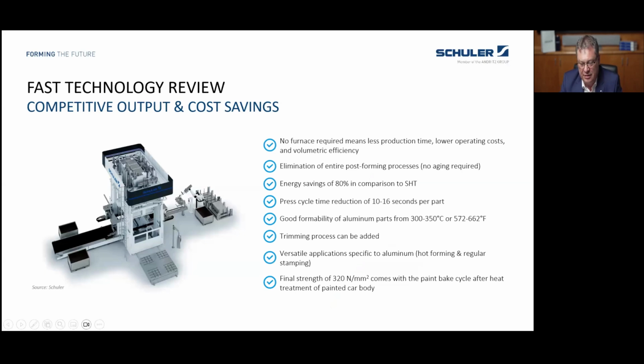Yeah, so to sum up all the aspects, the big benefit of the process is that we don't need any furnace for heating up the blanks, and this will of course lower the operating costs and also the required space for the line. We can also eliminate the entire post forming process, so the artificial aging is not required. We still have the paint bake cycle, but this comes automatically with the painting and drying of the paint of the car body. So due to the fact that we very specifically only provide the heat to the blank in a very small area, there will be a lot of energy savings.